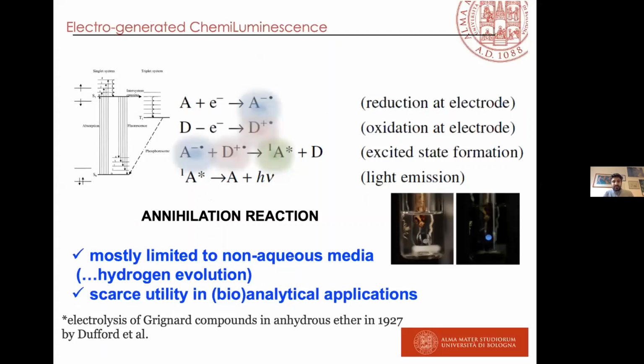So how can we generate light with electrochemistry? The main mechanism involves an oxidation process, generating a radical cation, and a reduction process, generating a radical anion. When you oxidize one species, one dye, and you reduce this dye, both are in the diffusion layer and can generate the excited state that emits light. This can occur between two electrodes or at the same electrode surface. At the same electrode, you switch the potential between the first oxidation and the first reduction. If it is the same electrode, we call it annihilation mode.